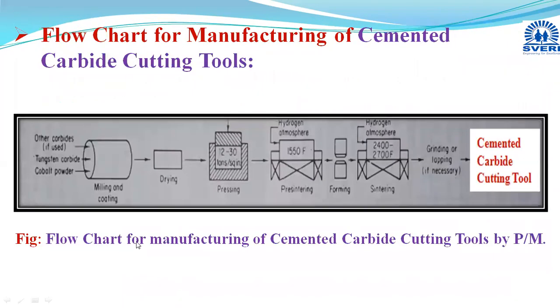Then manufacturing of cemented carbide, using different carbides like tungsten carbides and molybdenum carbides, and along with that, cobalt powder is used as a binder. You can use nickel or chromium powder also as a binder, or cobalt nickel compounds or cobalt nickel chromium alloys as the binders. Whichever binder you are using in this cemented carbide cutting tool, you have to take 20% of that binder, it may be metals or their alloys, and the remaining 80% will be of the respective carbides.